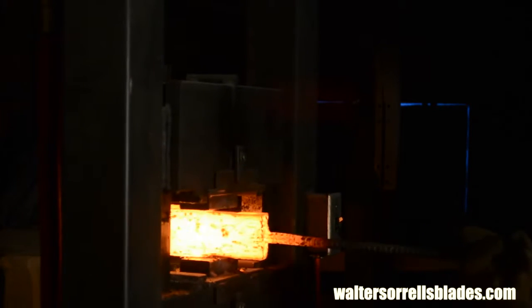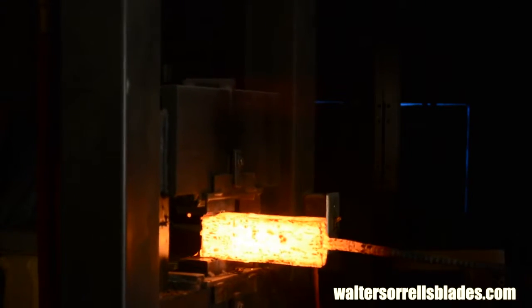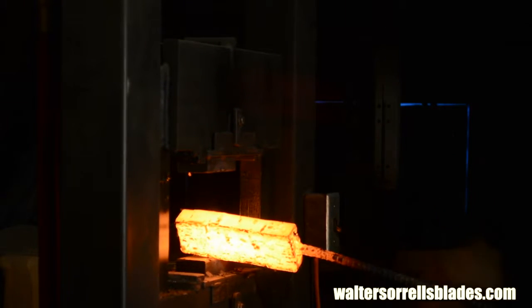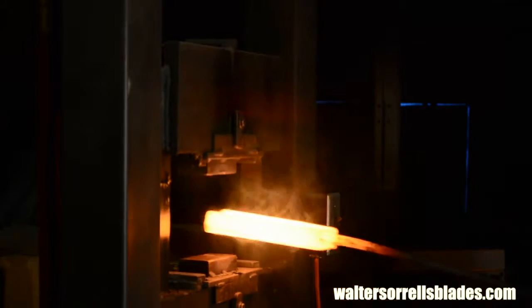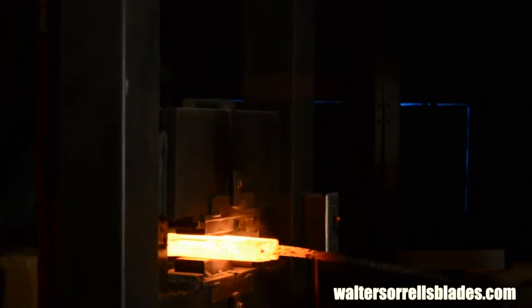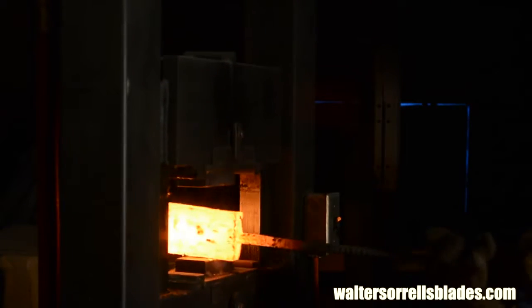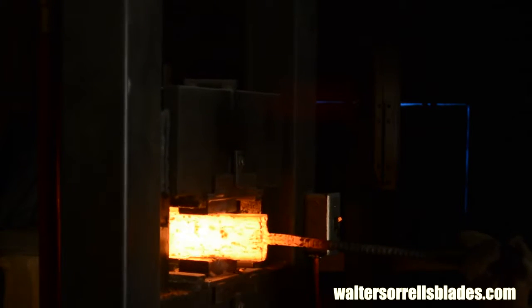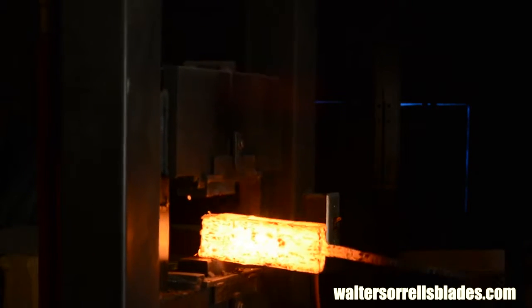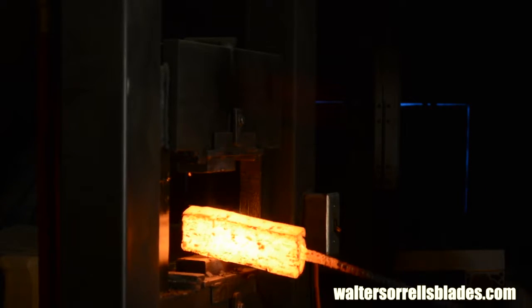Now I'll gently squash it in the press again just to make sure. I want to be dead sure I've set those welds all the way down the billet. Next, I'll usually flip it 90 degrees and square up the billet. This is a good test. If the welds haven't really set, the whole thing will start to pull apart here at this point. Then you go cry a little and kick the dog.